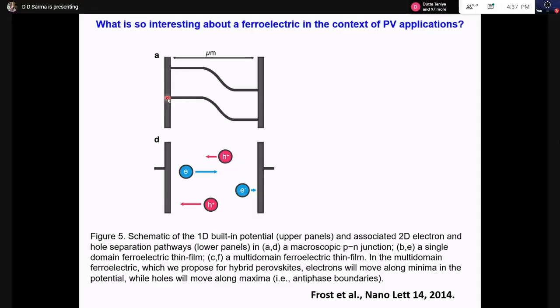Hole will have to be drifting this way. This electron that doesn't find the potential yet will be diffusing randomly, and only when it senses that slight potential that drives it, it will go that way. In the meantime, that means it will take a long time, it will have chances of recombining, the electron and hole, or getting trapped by many defects. And that's why you need to make the system as defect-free as you can, otherwise they'll act as trapping sites.